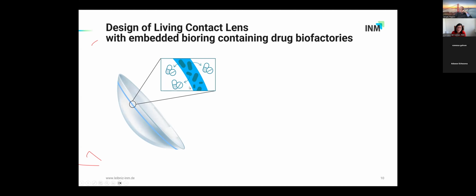This is what you see here. This is the bio-ring, okay? And if you would see inside, you would see this is the ring, the blue part, and in the ring we have the biofactories contained. The material in the bio-ring and the material in the rest of the contact lens are slightly different. To be more precise, the material where the PVA composition, where the biofactories grow, has a little less solid content. So here we use about 5% PVA and vinyl sulfone, and outside we use 8%.